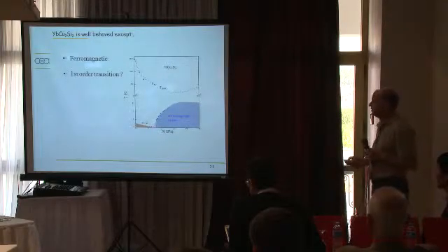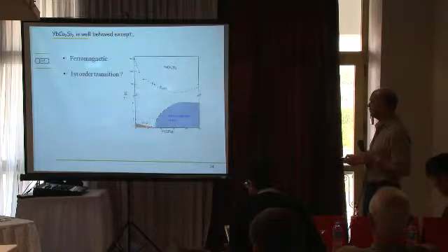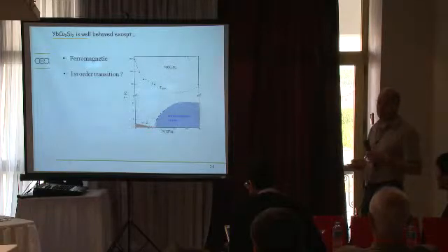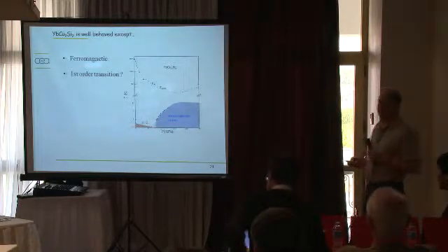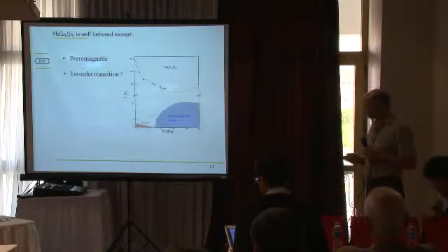The second surprise is that, after showing you nice pictures of our dilution fridge, you might wonder why I don't put any points in this region here. The reason is we've looked and we've never actually been able to detect a transition below about 1.5 Kelvin. So it seems that magnetic order appears suddenly at this temperature, and it could very well be a first order transition, which would also be compatible with the ferromagnetic state.